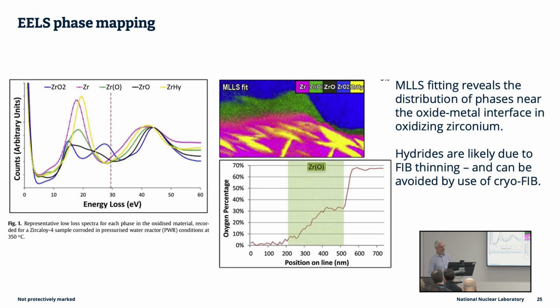Trying to do quantification like that of oxygen with EDS is perilous. It's much more difficult to do. Quantification of light elements is one of the areas where EELS really wins out.